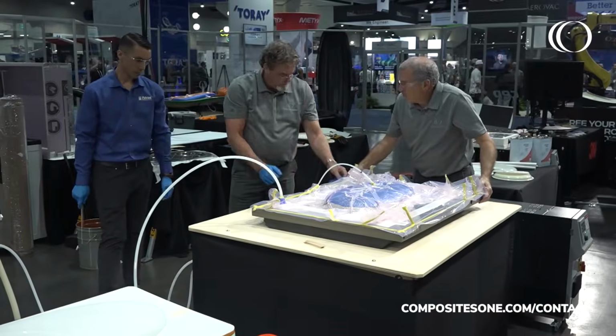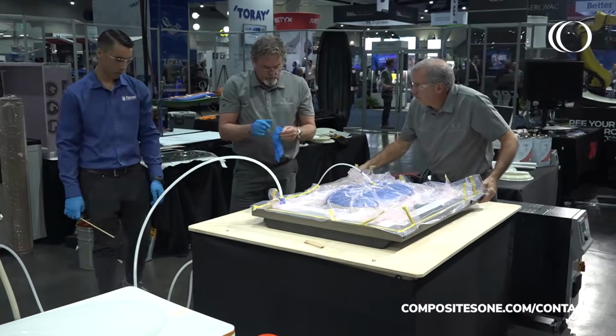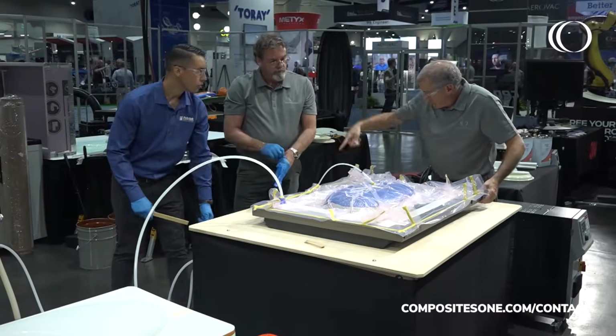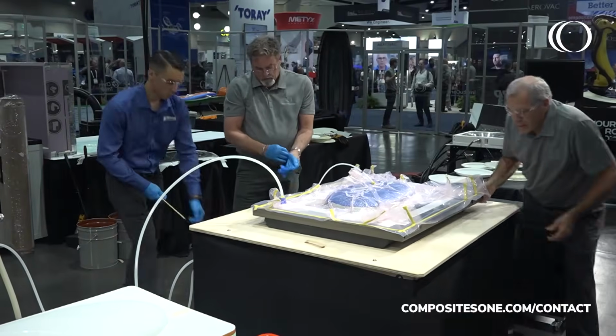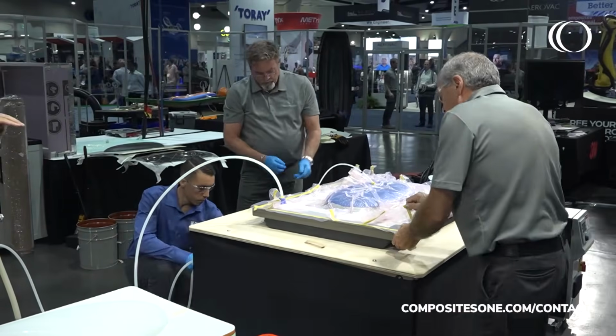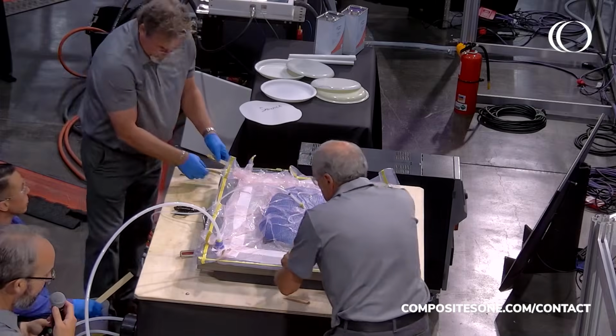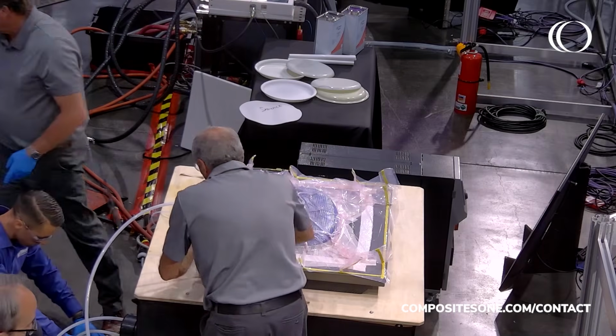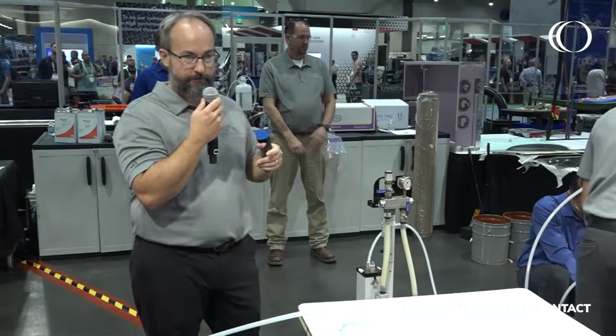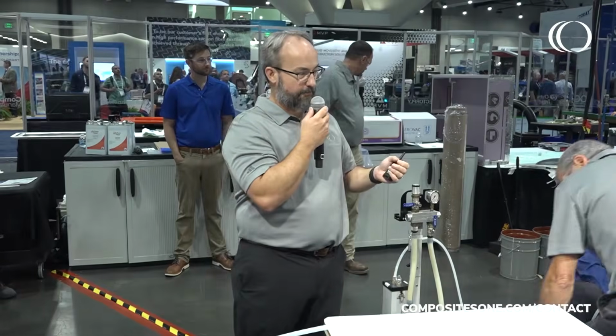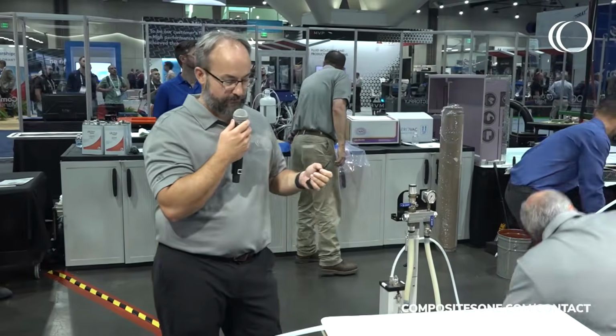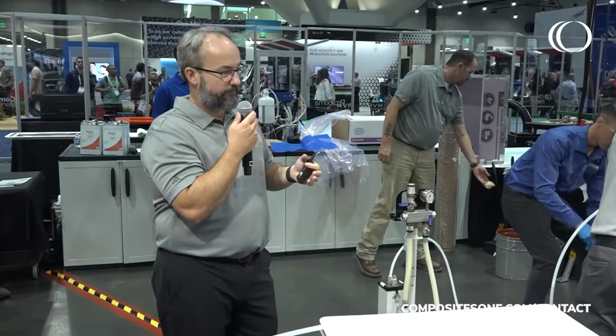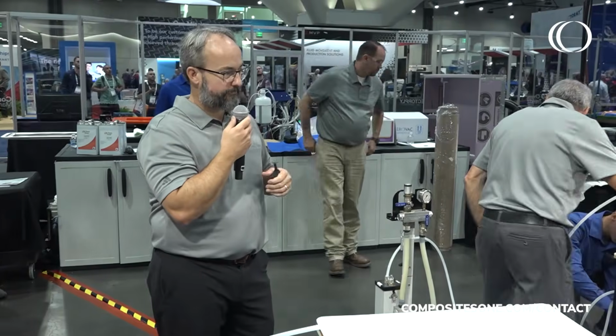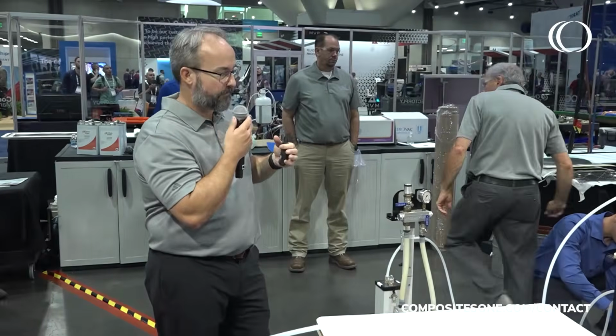Some of the other infusion strategies you could use is we could actually feed this around the perimeter and pull vacuum in the center of the part. One of the challenges with that is if you have any leaks around the perimeter, you'll be leaking air into the part where you're introducing resin. And we don't want to have any air in our part. So that's why we pull vacuum around the perimeter.